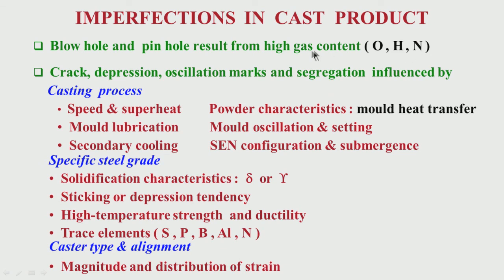All these processes control the amounts of solutes — oxygen, hydrogen, and nitrogen — in liquid steel. If they are beyond certain levels, you can find out to what extent pin holes or blow holes will be there. Everything depends on the value of these solutes in liquid steel at the time of casting.